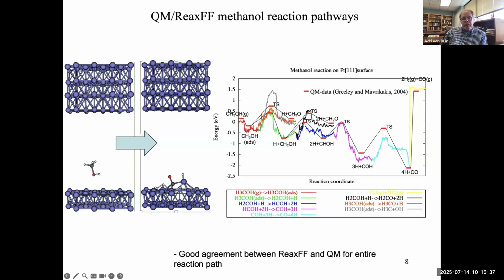So you see here the red bars are from quantum mechanics, and the ReaxFF wriggly lines are because this was done with a low temperature MD simulation, so there's a little bit of temperature noise. You see that the ReaxFF trajectory follows the DFT trajectory quite well. We get the transition states in the right place, at the right height, and we see all the intermediates show up in the right place.